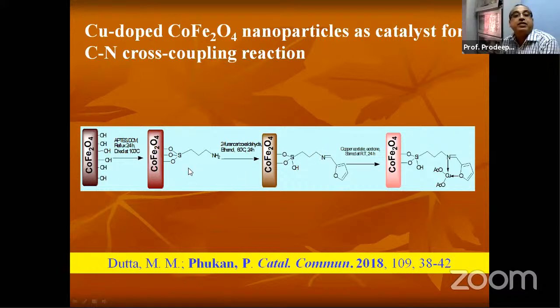Then what we did, we modified the surface property of this cobalt ferrite using some amine. Then we have taken furfuraldehyde. Then we made this compound. We made the Schiff base. Then on this Schiff base, copper acetate was added. Then copper was hooked onto the surface of the nanoparticle through a linker. This is actually the surface of the nanoparticle. We made a copper complex on the surface of the nanoparticle.